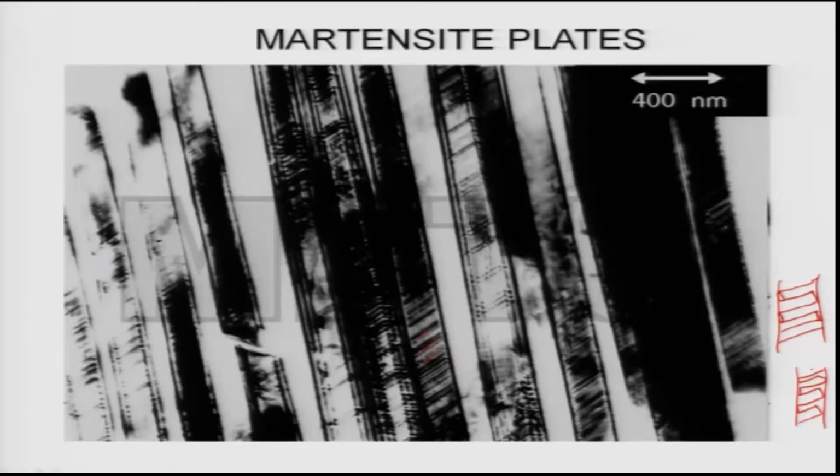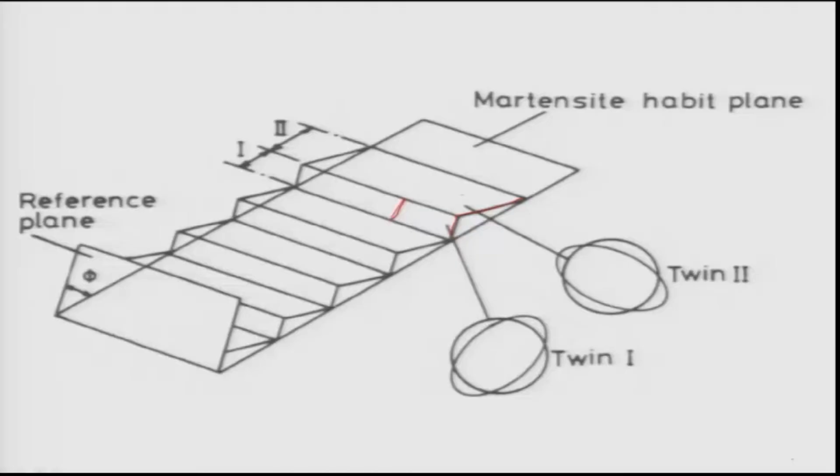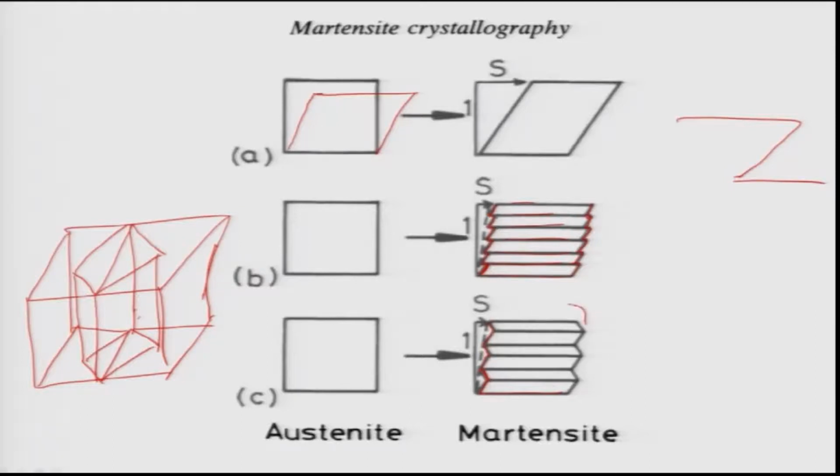These are visible when observed under a transmission electron microscope, and in the microscope things are actually projections from the original picture. So you do not see these orientations nicely, but one can do better imaging to show that at the end of the plates these twins are aligned at a particular angle. They can never be like this, it is not allowed. They will always be at an angle with respect to that. That tells you how the pack of cards can arrange themselves. The picture I showed you earlier, or even this picture, is better. That is how things actually happen.